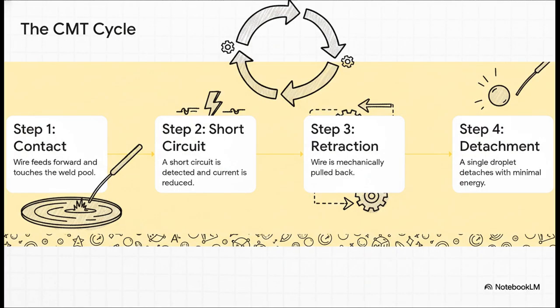1. The wire moves forward and touches the weld pool. 2. The machine's brain instantly detects that short circuit. 3. The current is immediately cut to almost zero. And 4. The wire feeder physically pulls back, snapping off one single droplet. And this whole cycle happens up to 70 times every single second.